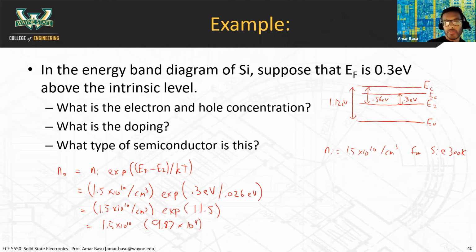Okay, so the reason I'm belaboring this is so you can see that the position of the Fermi level determines the exponential, and this will basically be a multiplier for the intrinsic carrier concentration. The intrinsic carrier concentration will get multiplied up by this exponential term. The farther EF is away from EI, that carrier concentration will go up very rapidly.